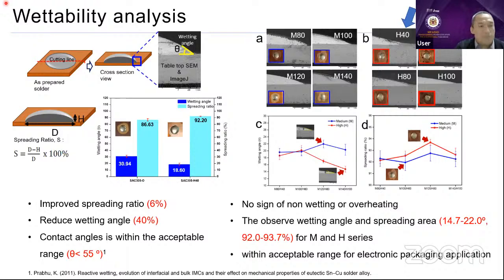Okay, and then we go for the wettability testing. So this one is for the wettability analysis, and I will try to go as fast as possible. When we run the wettability, we found that the high mode can give us a much better wettability compared to the medium, right? And when we check the wetting angles, they produce a very nice wettability compared to the others, right? Sorry, I need to go faster because I'm taking a very long time, I think.